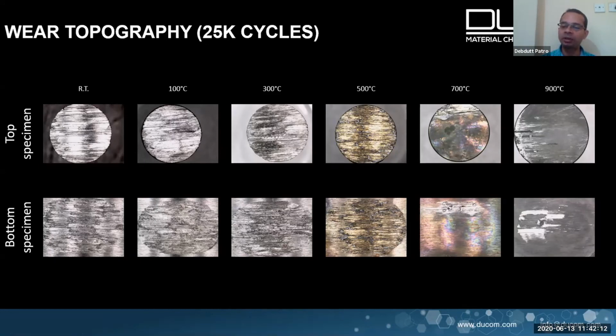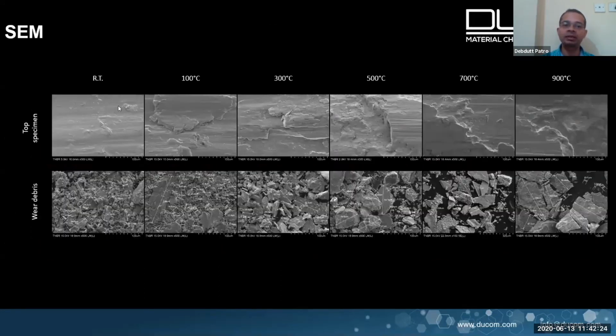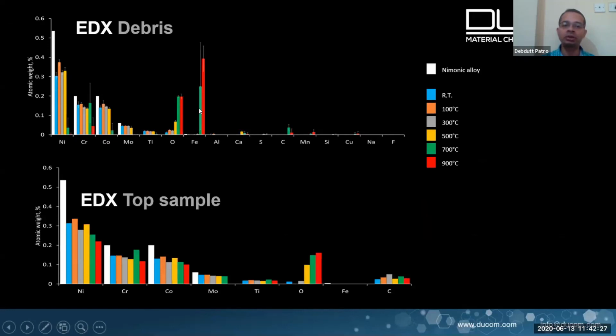So there is some kind of material on the surface, and this is the third body which forms. So typically what happens is, and this is some EDX results to show the composition of the material on the top surface. So you see that the red bars here at 900, and that is for oxygen. So the levels of oxygen actually are fairly high when you go to high temperatures. So the material starts oxidizing, and when they oxidize, the initial metal to metal contact is prevented. There is a third body which comes in the contacting surface, and that reduces friction and wear.